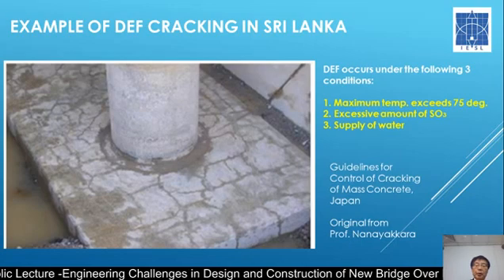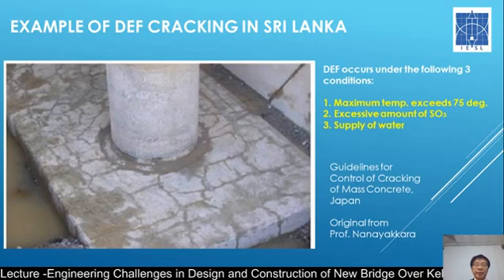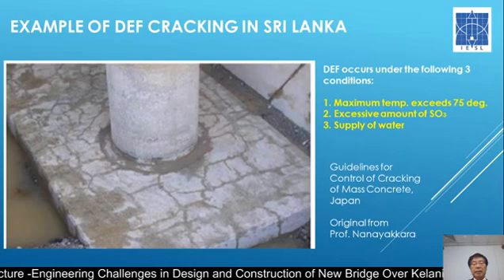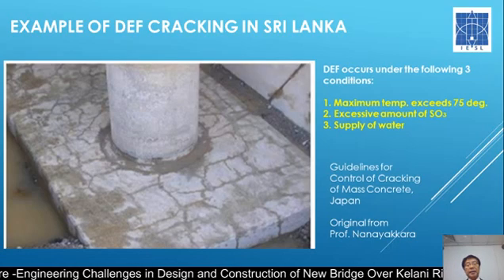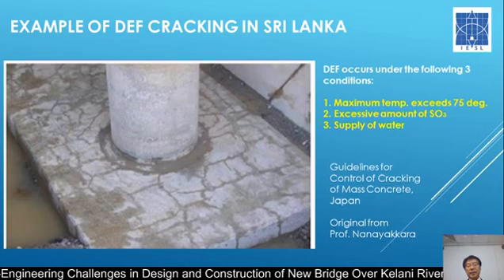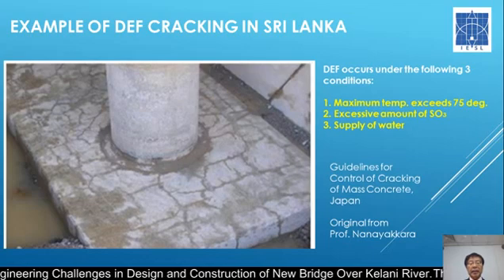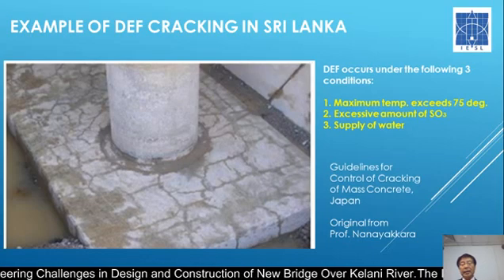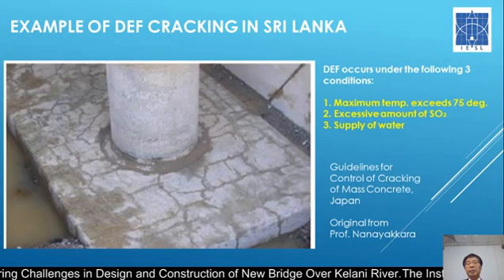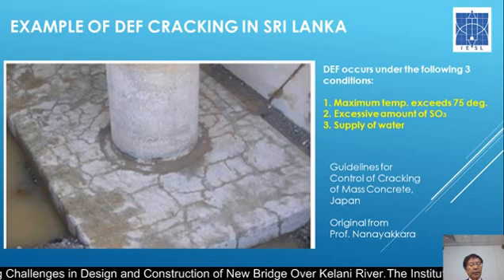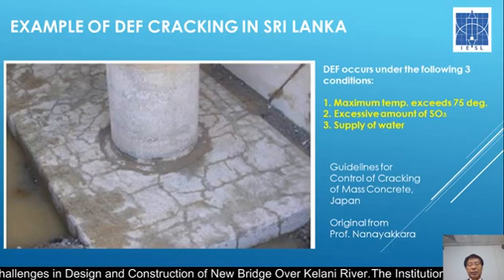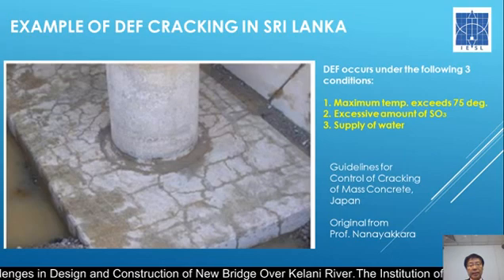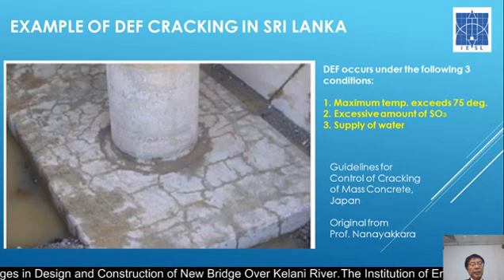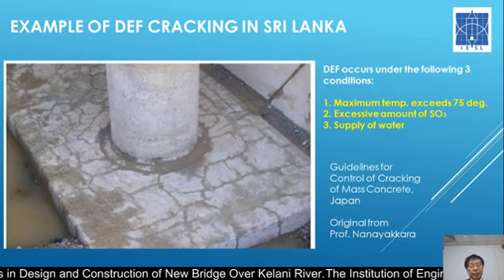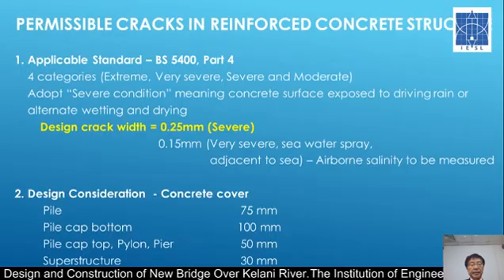Also, if water is continuously supplied after the concrete is cast, it will expand, trigger, and develop cracking like that shown. Some of the cracks are a few millimeters in width and not acceptable for a structure. So this is a very important phenomenon that we have to avoid, such cracking.